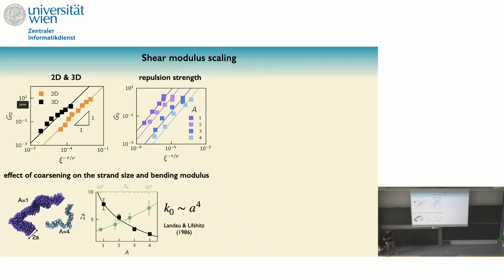And the reason why they do not fall onto a master curve is that when you form your system, if you change your preparation protocol, your microstructure is changing. But one important thing is that the size of your strands would change as well. And if I told you that the macroscopic elasticity is dominated by the bending, then the size of the strand is very, very important. Then what you can do is measure the diameter of your strands, and you see that if you change the way you form your system, by changing the preparation protocol or by adding electrostatic interaction or not, the radius of your strands will vary a lot.